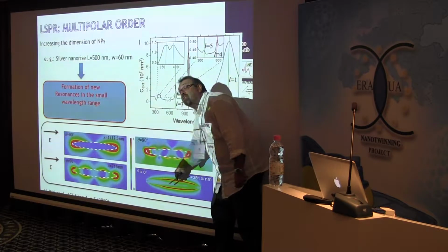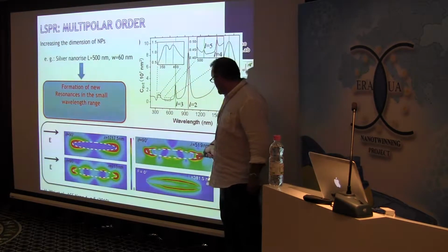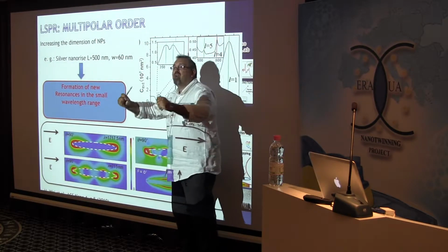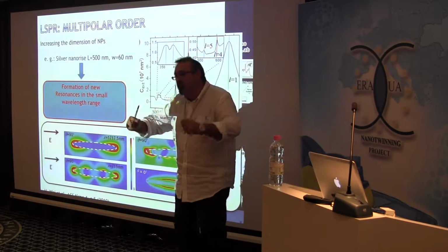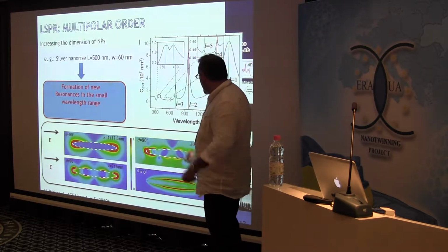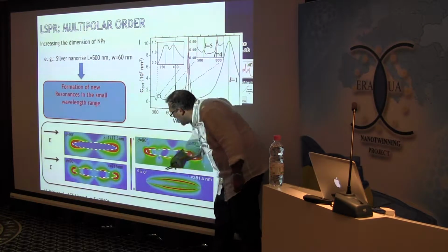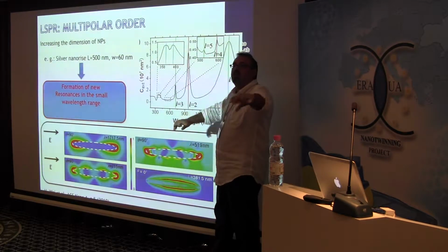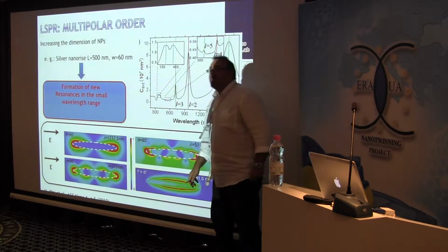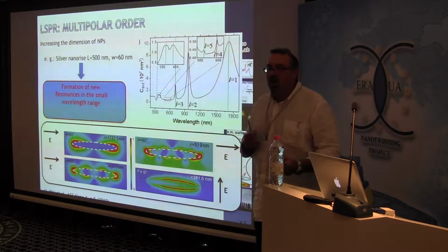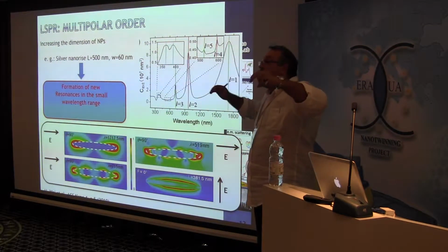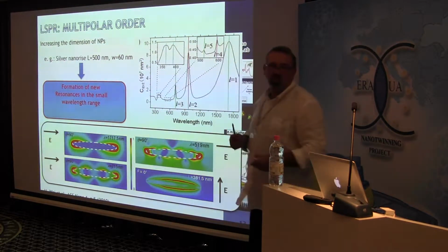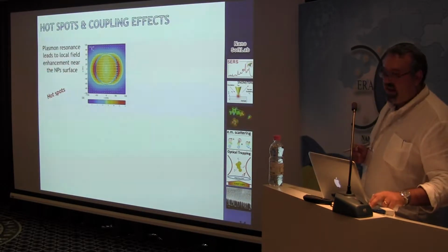So you will see hotspots again, but the difference in comparison with before is that in this case, the hotspot is very confined, a few nanometers, a few tens of nanometers perhaps at the edges. If you excite this nanoline, this nanoantenna, with a field that is polarized like that, you have an elongated hotspot. So in this case, the field enhancement is typically lower, but the fact that you enhance a larger area is of particular importance for molecular detection in cells, and we will see it later.